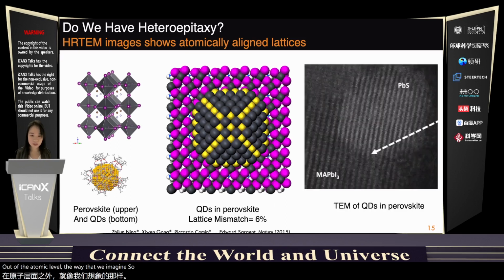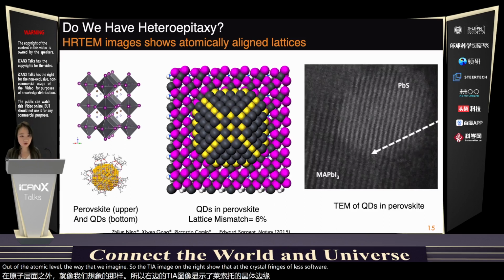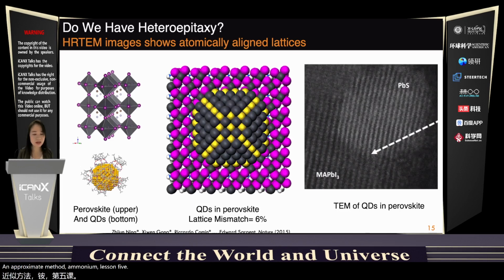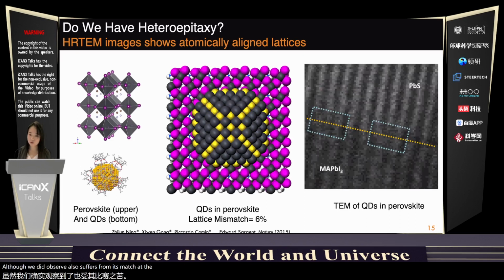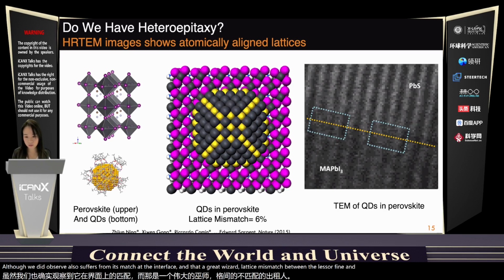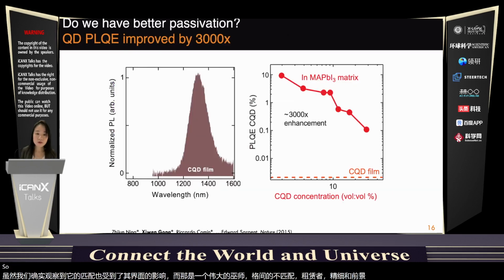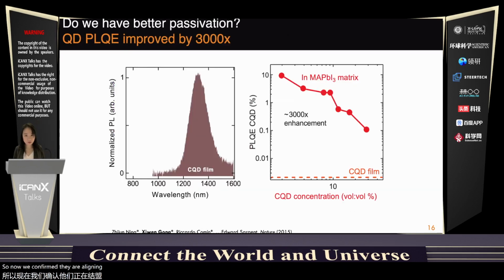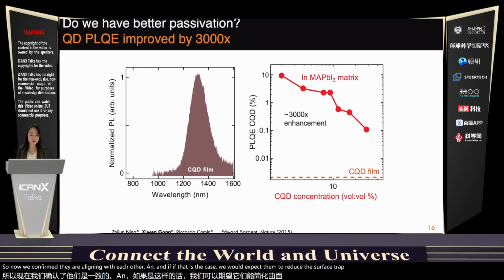The TEM image on the right shows that the crystal fringes of lead sulfide and perovskite, methyl ammonium lead iodide perovskite particularly, align with each other, although we did also observe certain mismatch at the interface, and that agrees with a lattice mismatch between the lead sulfide and perovskite. So now we confirmed they are aligning with each other. And if that is the case, we would expect to reduce the surface traps and therefore get brighter emission.